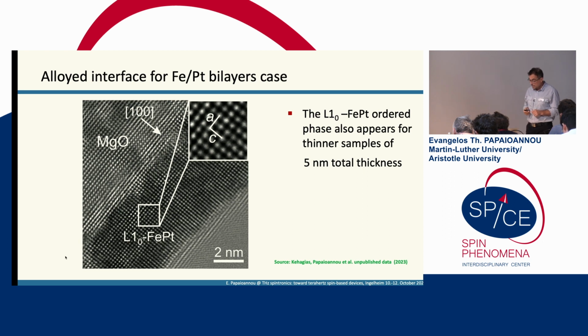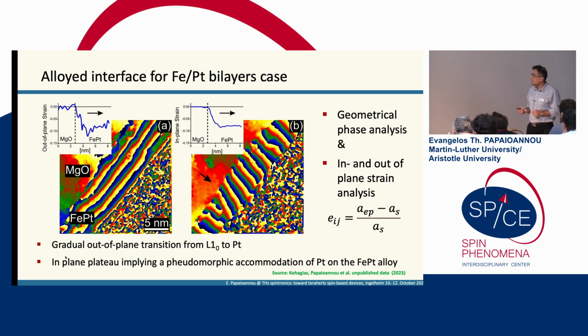And it's not only this. This is a special structure which I would say surprises us. And we did some phase analysis of our electron microscopy images. And in principle, you can have a look at these two graphs which come from this analysis. So here we look at the strain that is induced along the